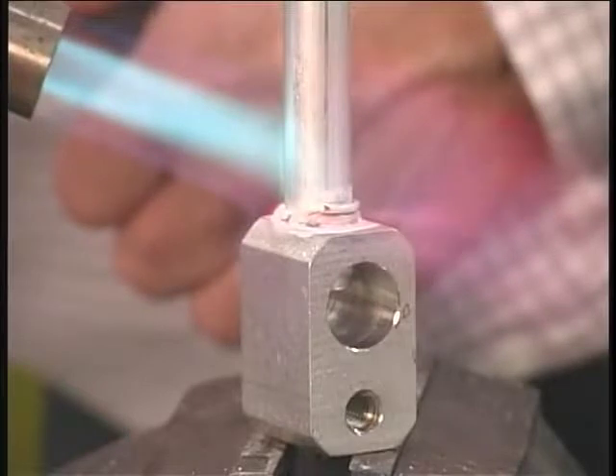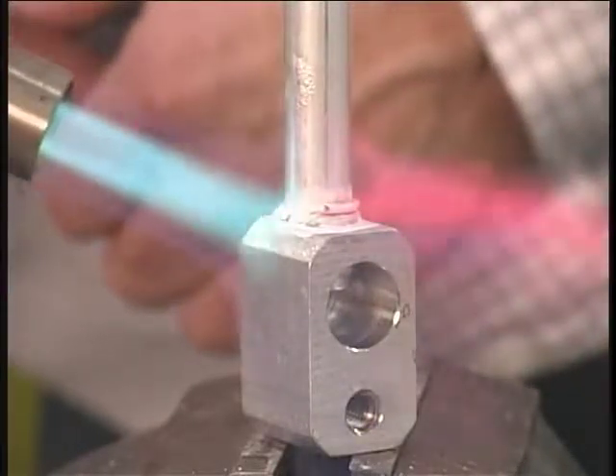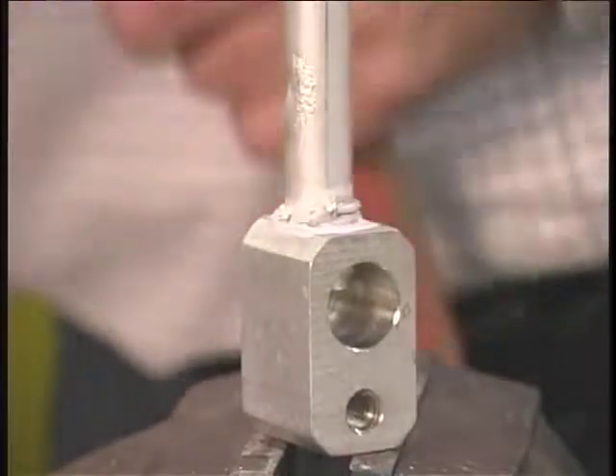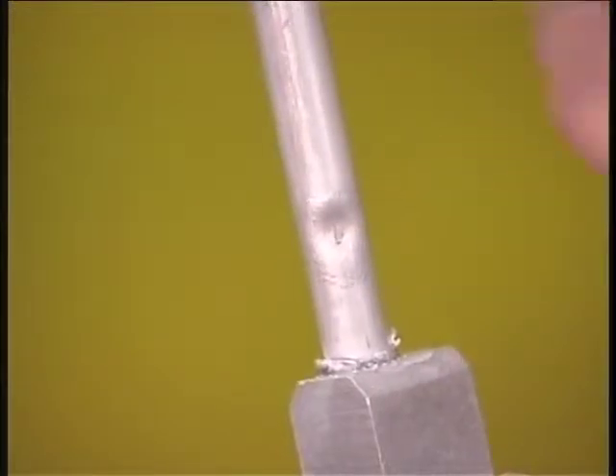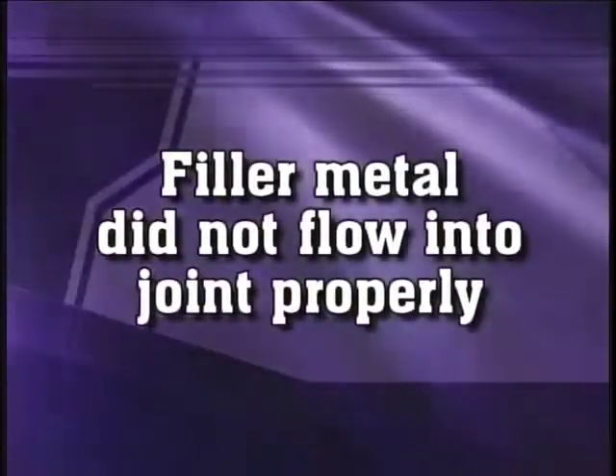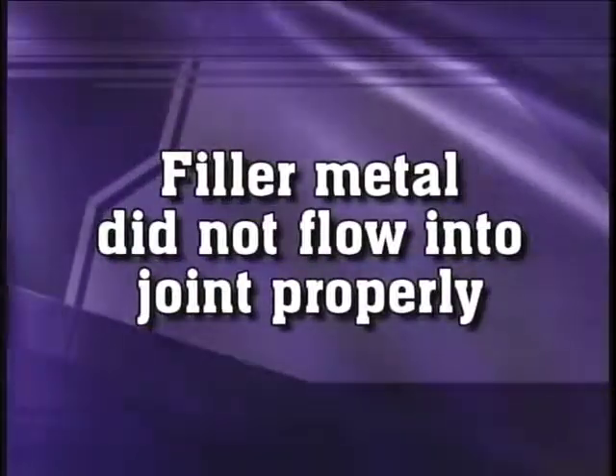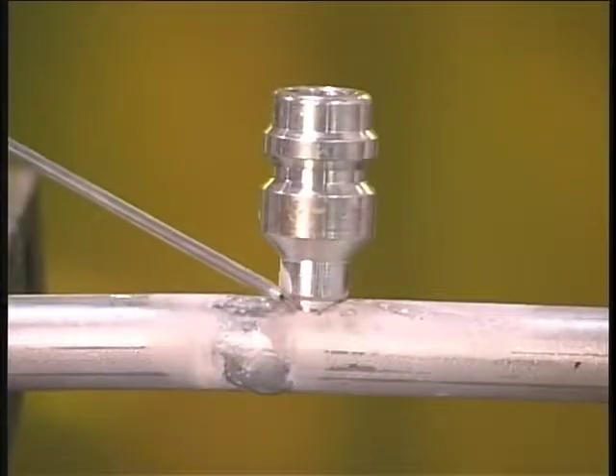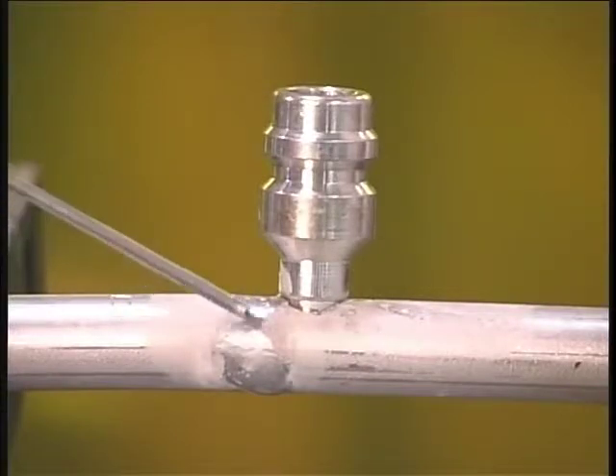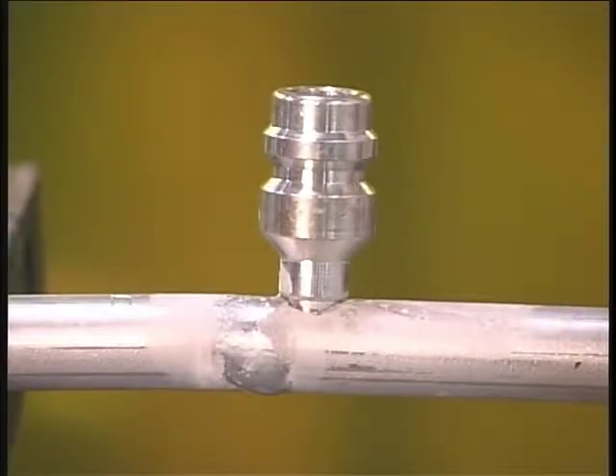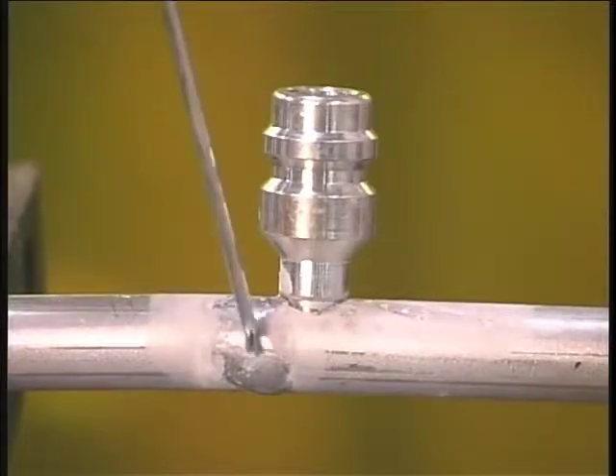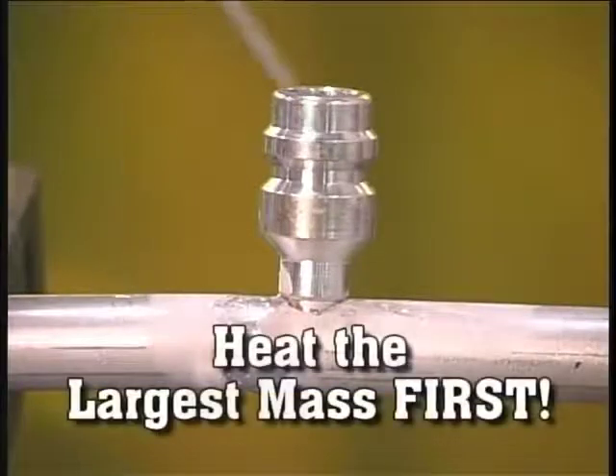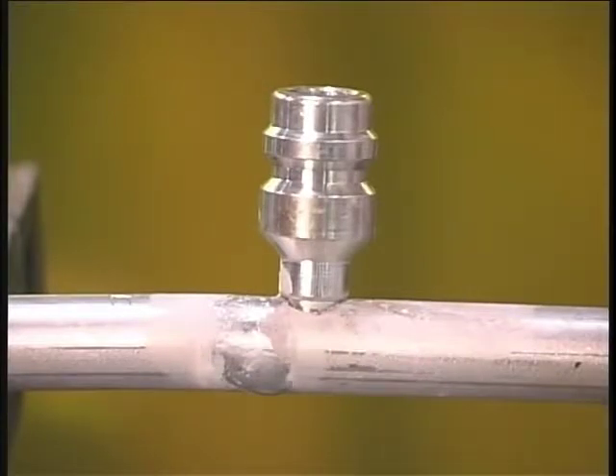Avoid the frozen turkey syndrome. Too much heat applied too fast caused the outside to melt before the inside became warm enough. Localized blistering or melting indicates keeping the torch focused on one area too long. Joint area was not hot enough to melt the filler material. The molten flux and filler will always migrate toward the hottest area they can reach. If the filler melts but flows away from the joint, it's another case of too much heat to the wrong place. Heat the part with the largest mass first and let the joint conduct heat evenly until it's hot enough to melt the filler alloy.